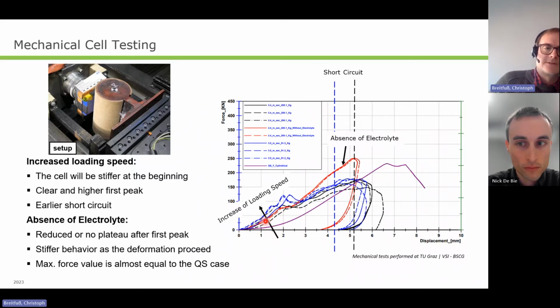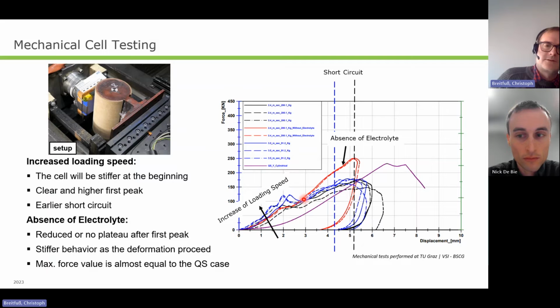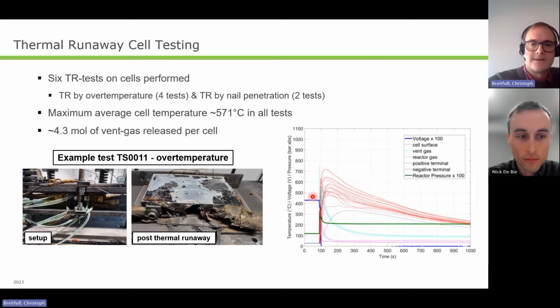Also interesting, the absence of electrolyte results in less peak, or less plateau after this first peak. And as the deformation proceeds up here, we are very stiff compared to the same configuration in black with electrolyte, and we have the same slope as in the quasi-static test.